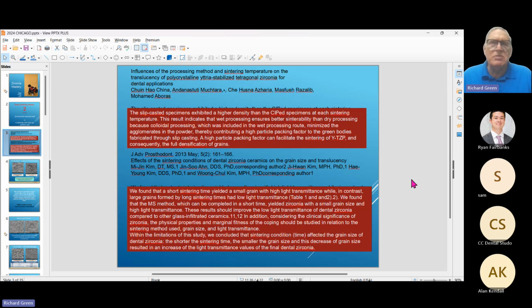But that's from 2013. That's 11 years ago that they were discussing this ability to rapid sinter. And even that long ago, they identified certain things that were more helpful than others to make sure that they had, as the slide showed, zirconia that actually sintered well. And here they're saying in the top study that slip casting, which is what we do, our colloidal process, ensures better sinterability than dry processing. A high particle packing factor can facilitate the sintering of zirconia and consequently the full densification of grains. So what they're saying is the more particles that we have in a given space, the better they sinter. Makes sense because they're closer together.